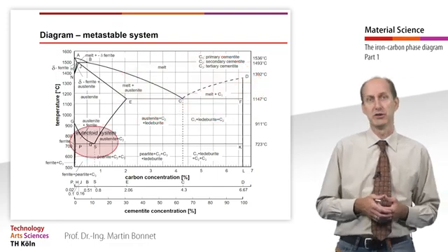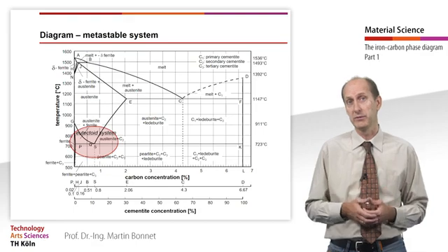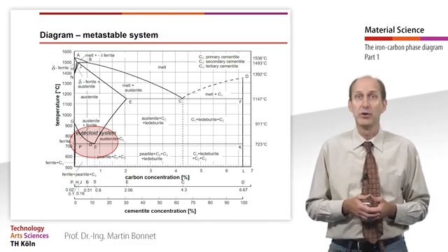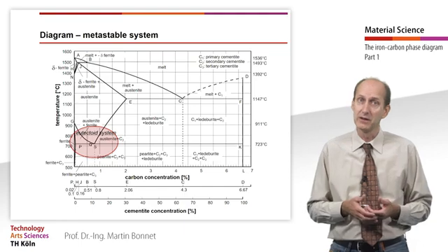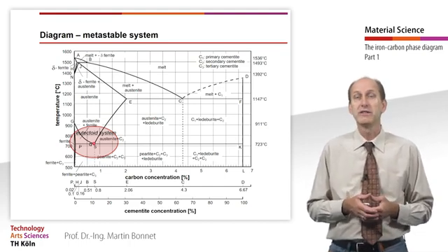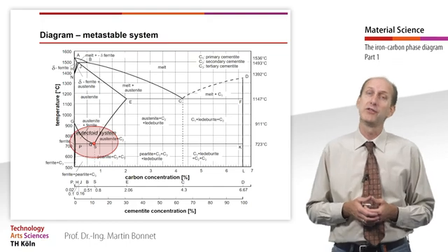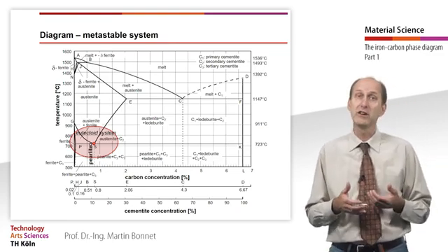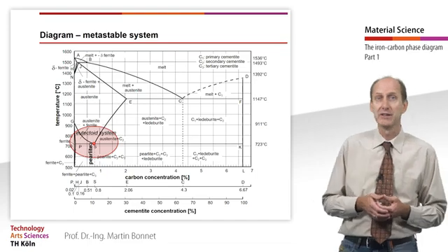The area at low temperature and low cementite content in the phase diagram also reminds us of a system with decreasing limited solubility in the solid state. Unlike the eutectic system, the transformation starts from components dissolved in each other in the solid state — the austenite. As this system is very similar to the eutectic, it is called eutectoid. The eutectoid point is at 0.8% carbon and a transformation temperature of 723 degrees Celsius. This eutectoid structure is called pearlite and consists mostly of soft, tough ferrite layers with cementite lamellae, which considerably increase its hardness and strength.